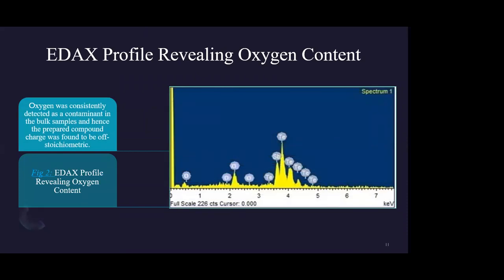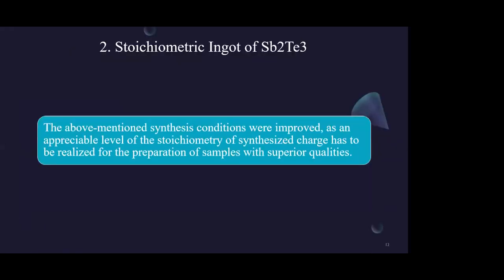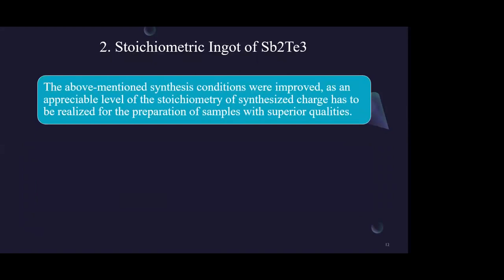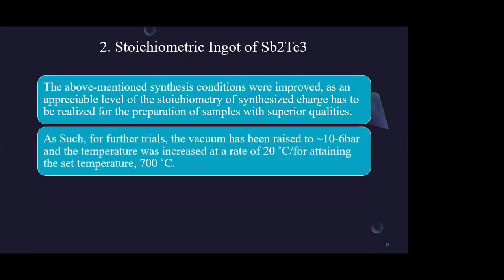Oxygen was consistently detected as a contaminant in the bulk samples, and hence the prepared compound charge was found to be off stoichiometric. So further analysis was done. The above mentioned synthesis conditions were improved, as an appreciable level of stoichiometry of the synthesized charge has to be realized for the preparation of samples with superior qualities.